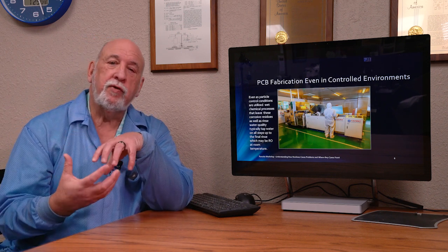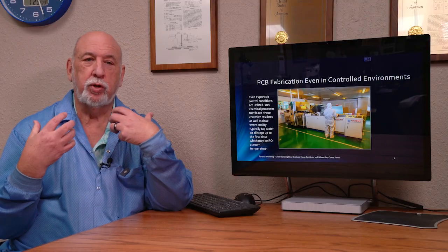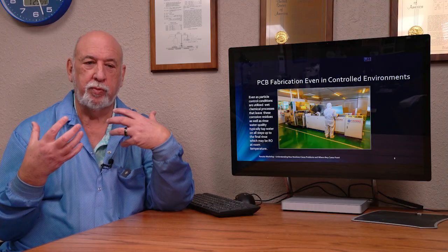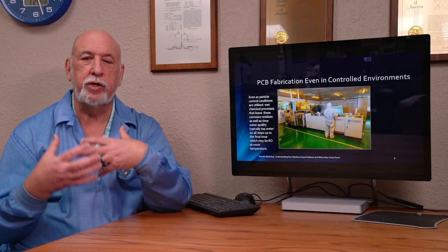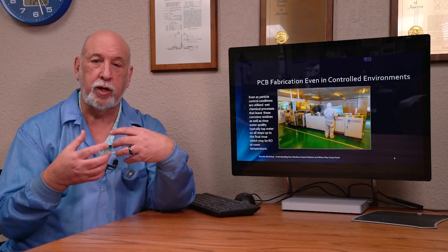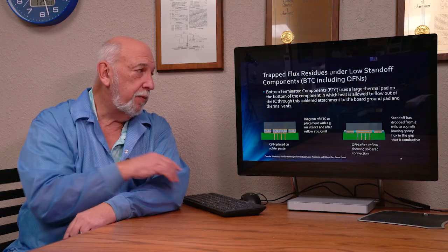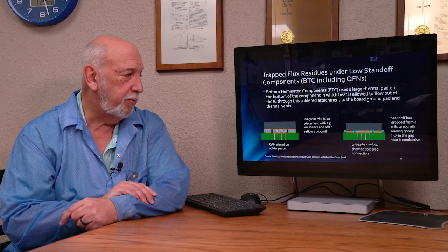When we control the environments in fabrication, one of the things that we're trying to do is control the particulate count. Everyone is more concerned about airborne particulates and debris than they are about the chemical understanding. So we have to add the chemical understanding to the residuals, both ionic and organic residues coming from the fabrication process. And water quality is one of the biggest.